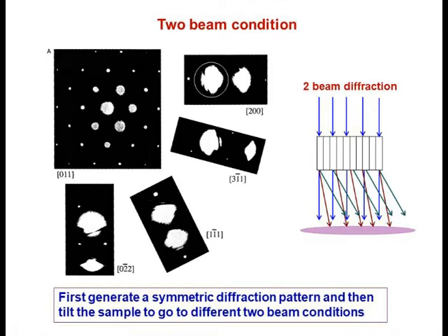Depending upon the type of defect present, from some regions there is scattering taking place, but the variation in transmitted beam intensity is due to scattering because of this particular set of planes. So this image is coming because of scattering which has taken place in a specific direction. Only these two spots, the central one and this spot, are considered. This is called, in microscopy parlance, the two beam condition. This is the condition under which we have to image dislocations always.